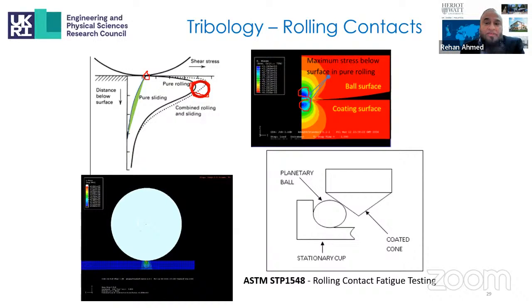in this simulation as well. And rolling contact fatigue tests can be performed using a modified ASTM STP1548. In this test configuration, the coated specimen, which is a cone or a ball, rotates against 3 planetary balls until the specimen fails. And these tests are usually performed in lubricated conditions. Now, these tests give us 2 important pieces of information. The first one is the rolling contact fatigue life in terms of number of stress cycles to failure. Remember, in sliding wear, we were calculating the wear rate. Here, we are calculating the number of stress cycles to failure. And secondly, the failure mode of the coating in rolling contacts using any sort of post-test evaluations.